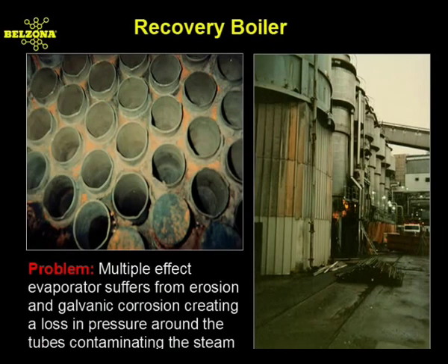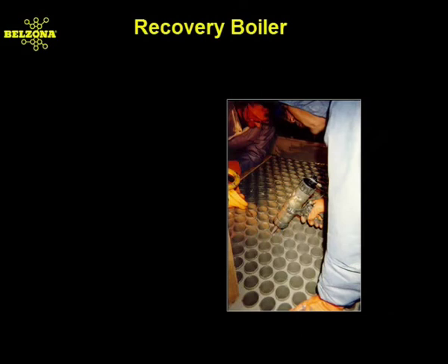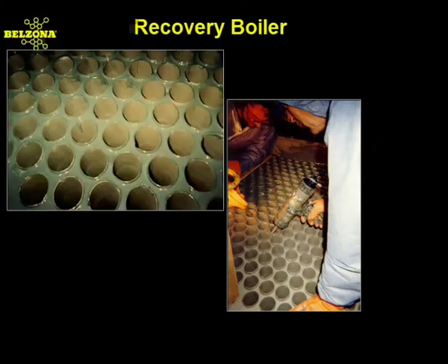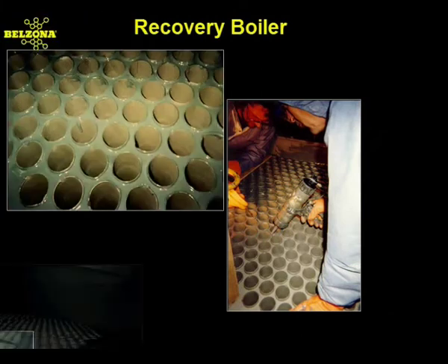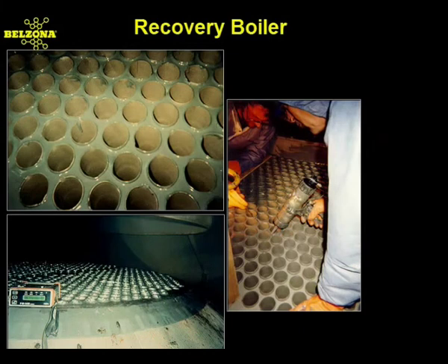In April of 1991, a pulp and paper mill in British Columbia, Canada had grooves eroded and corroded around the tubes in excess of 1/8 of an inch. In this case, leaks had developed between the stainless steel tubes and the mild steel tube sheet face, contaminating the process steam. Belzona's densely cross-linked heat-resistant polymeric coating material has been used to successfully eliminate this process of erosion corrosion of the substrate.